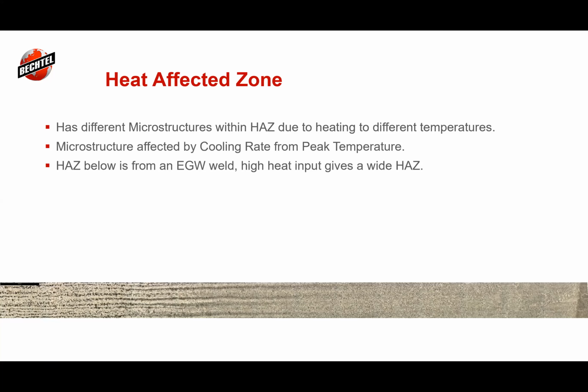It uses like 500 kilojoules an inch of heat input, which is massive amounts of heat input. So you have to use that with like an A36 type steel. You use it with like a 516, like unnormalized material. But the reason why I like it is the heat affected zone is really huge.